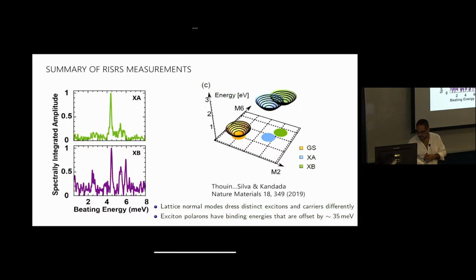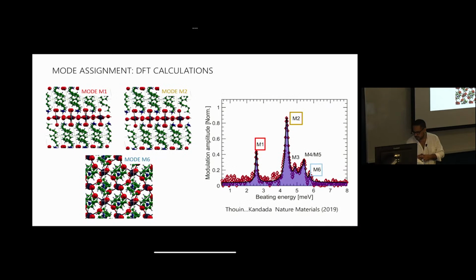So let's remember this spectrum here. This is a spectrum of the resonant impulsive stimulated Raman injecting photocarriers. But now let's do the experiment. Let's tune our laser to XA and then to XB. Now let's look at the excitons. We expect that if it's a vibronic progression, all of these features are replica of the same electronic transition. They should reflect the same electron-phonon coupling as the origin of the transition.